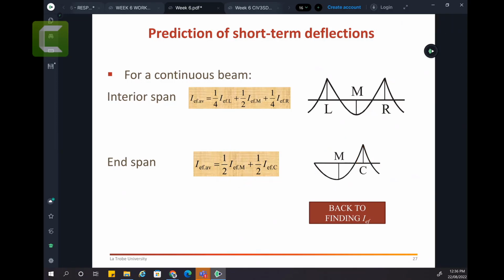If you want me to summarize this in the procedures, first you need to calculate the I effective, which I bypassed just now. I'm going to go back and show you how we calculate an I effective at one section, whether here or there, because it's a function of loading. So it's changing, right? After you do this, you calculate it at the other end, as applicable. For this case, we have only this end to worry about because here the I is 0. Then you average them as shown. You take 50% of the I value at C and 50% of the I value at mid, and you've got your I effective average. That will complete that deflection delta S formula I talked to you about.